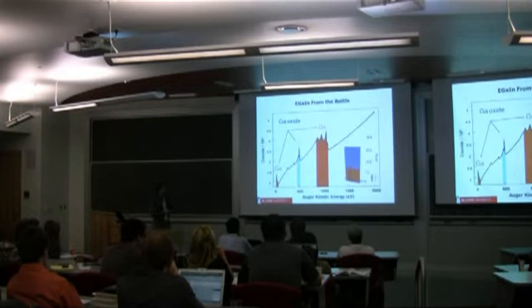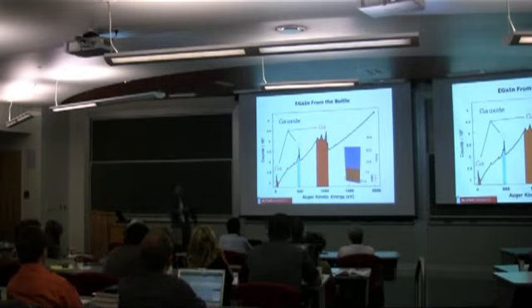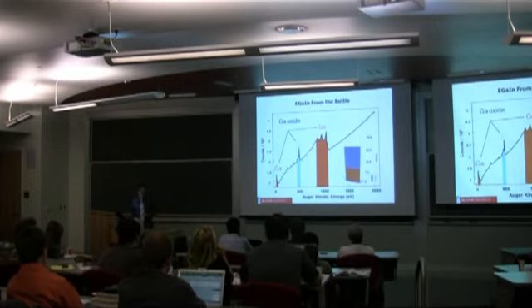Just to prove it to you, this is Auger spectroscopy of the surface of the metal. And the take-home message from this is if you kind of do an elemental breakdown of the surface, you primarily have oxygen, gallium, and a little bit of indium. So again, indium is just there to lower the melting point. It's really gallium that we care about. And gallium has a lot of interesting properties, which I'd be happy to talk about at the end of the talk.